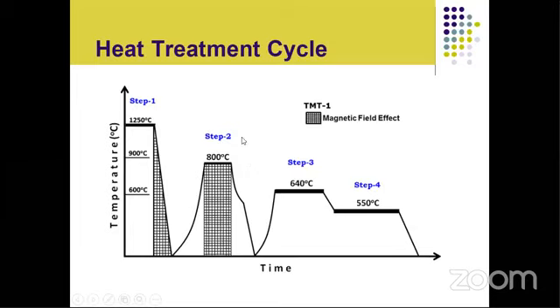So in the TMT region, thermomagnetic treatment region, actually alpha 1 phase will respond and its volume fraction will increase and coercivity is developed. And in the step aging treatments, actually solid state diffusion will take place, and the iron and cobalt which was present in the alpha 2 phase will migrate towards the alpha 1 phase, and copper and nickel which was present in the alpha 1 phase will migrate towards the alpha 2 phase. So this migration will create a composition gradient between alpha 1 and alpha 2, making alpha 1 a good ferromagnetic and making alpha 2 as least ferromagnetic or non-ferromagnetic.